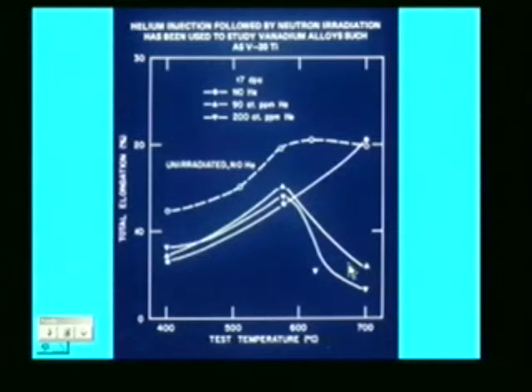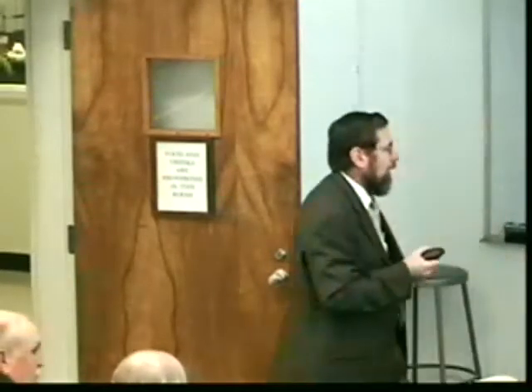significant drop in ductility. So we're showing several techniques, and the reason is that when you're doing simulations and studying the fundamental behavior, one technique will not do it. You need every piece of the puzzle that you can get. So we use various techniques. For example, if you're going to dope with nickel, you have to understand the effect of adding the additional nickel. So one experiment cannot simulate behavior.